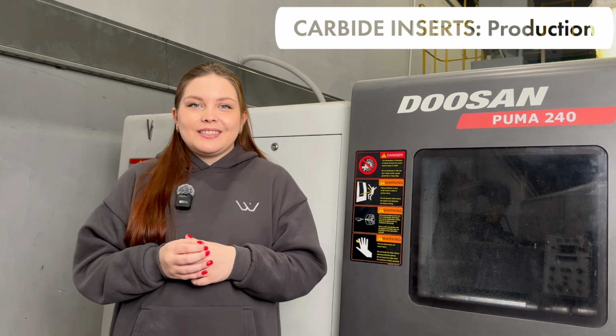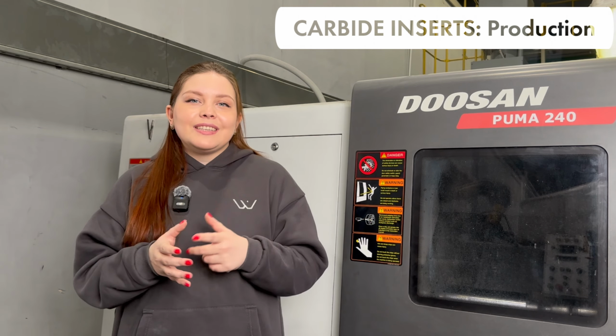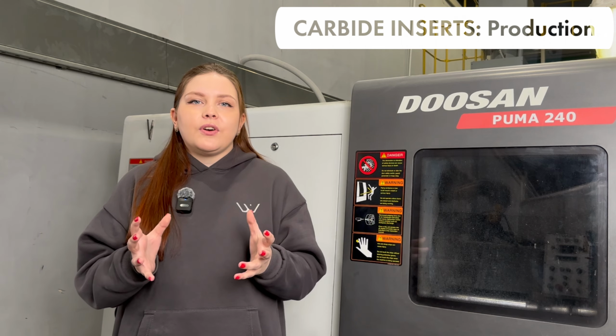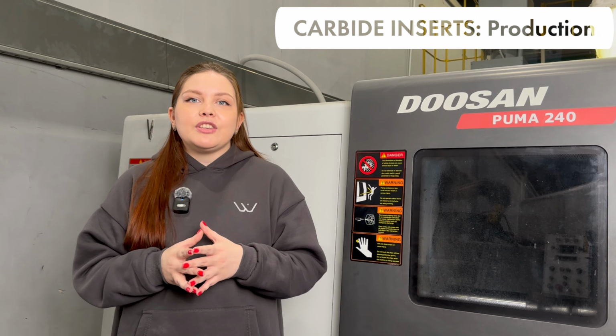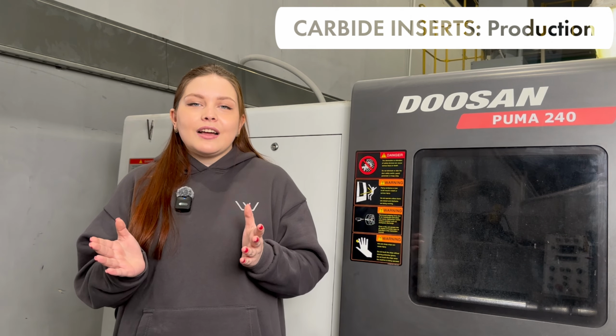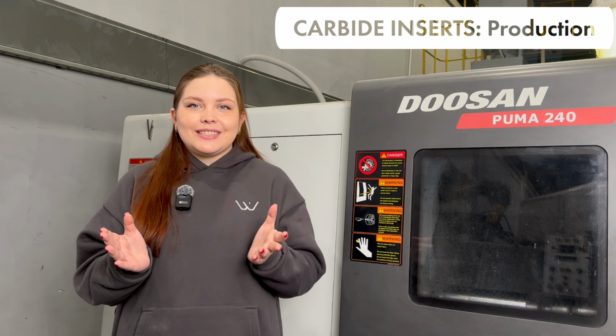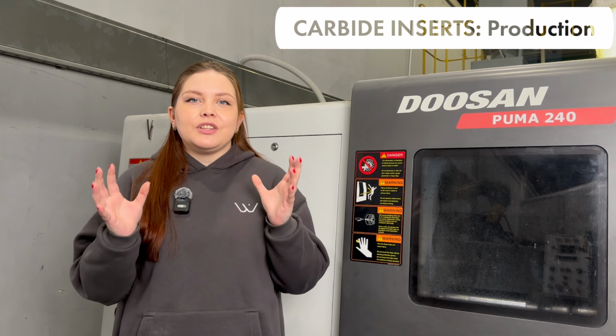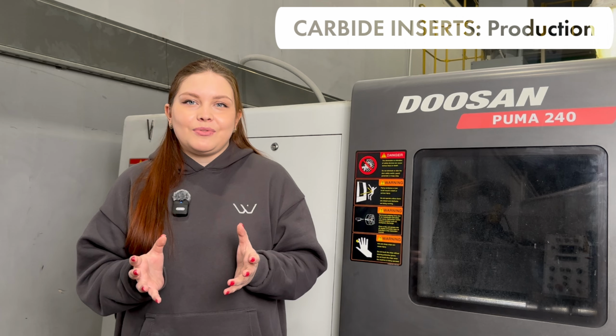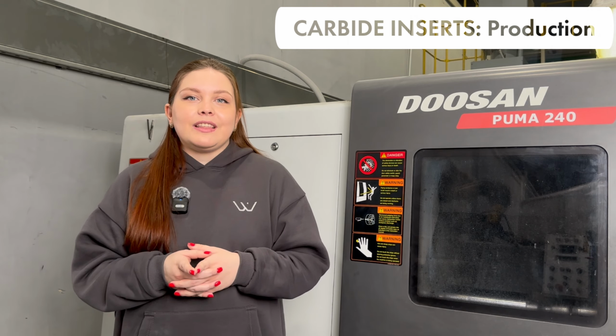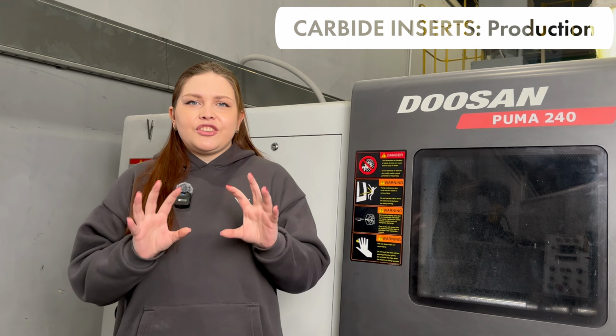Now comes the real deal, sintering. The pre-sintered mass goes into a super hot furnace. The temperature here typically ranges from 1300 to 1600 degrees Celsius, where it transforms into a hardened and durable carbide material. After the heat treatment, the carbide is tough but not in the right shape.